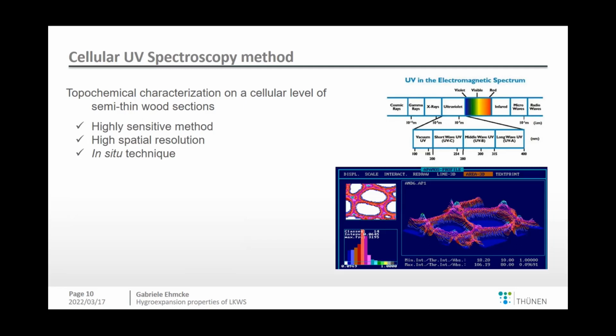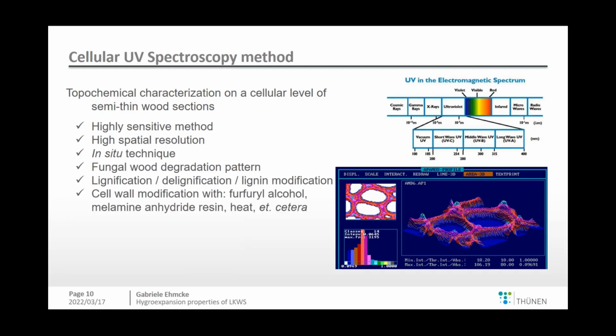So you don't destroy everything and just look at single components. You have just the wood tissue as it is, or as it was in the board or in the larger sample, and you can look just at this point. So you are able to analyze fungal degradation patterns. You can analyze lignification, delignification, or lignin modification. So it's also very valuable for investigation of the wood formation. There you can follow the lignification of the cell walls.